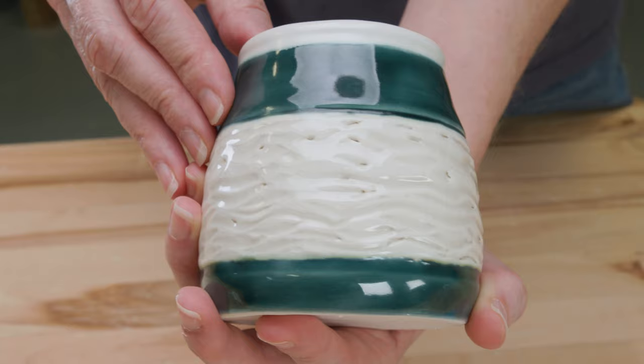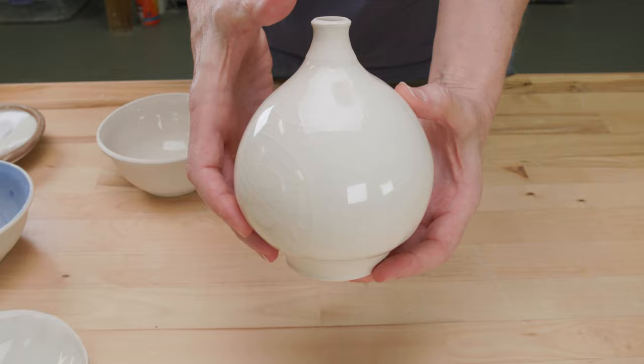And here are the results. There are cracks all over the pieces. It didn't seem to matter what clay I was using — the cracks showed up on the porcelain and the red clay. I love how it covered over the Amaco Baby Blue underglaze. The thick glaze smoothed right over it and produced the same type of cracks. Here's the bowl without the underglaze but with the swirl — where the glaze was thick, the cracks were farther apart, and where it was thin, you got tighter cracking. Here's the shell bowl — the cracks seemed to follow the undulations on the surface, which was cool. Here's the teardrop vase — nice wide cracks along the center part and tighter cracks on the top and bottom. This one was the layered piece: the one coat side produced smaller cracks, the two layered side resulted in bigger cracks, and the three layered side were even farther apart.